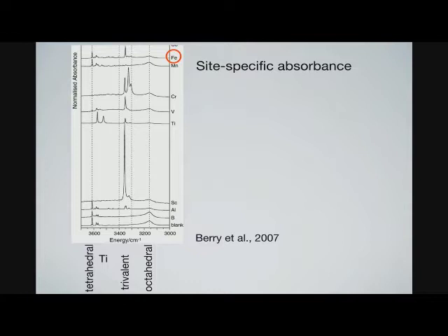And yeah, I should get a better slide for this, but basically, people like Andrew Berry have doped olivine with all sorts of materials: iron, manganese, chromium, vanadium, titanium, scandium, for example, that have different valences, different charges of their ions, and then looked at the infrared spectra of the hydrated olivine. You can basically fingerprint each particular defect, since each has a particular absorbance in the infrared spectroscopy.